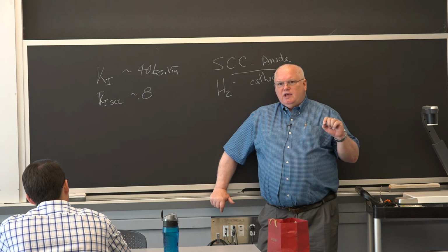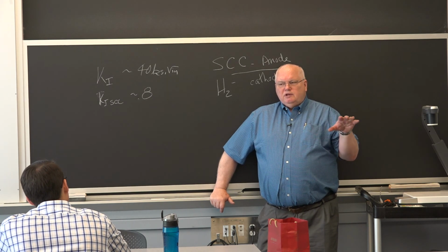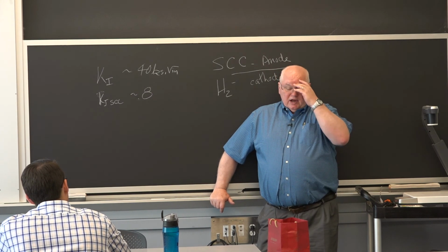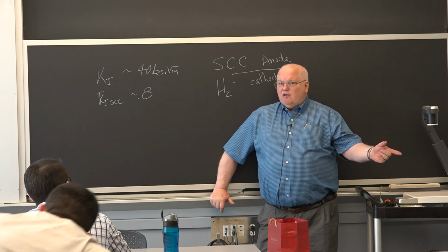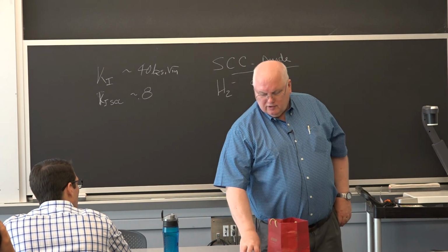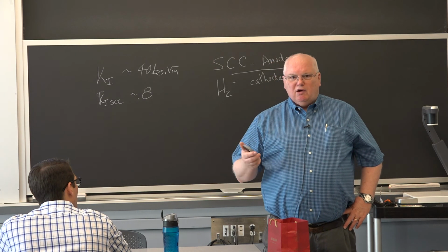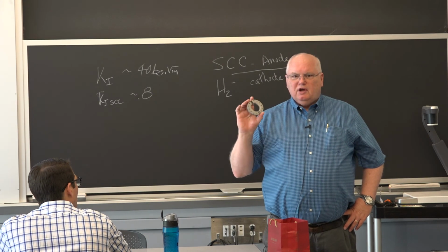And they had fixed it. They had gone from the T6 heat treatment on this washer to a T73. And when they discovered this, they said, oh, we should tell some of the other aircraft groups that there's this problem. So at the time, there were 1,300 Hawks, Seahawks and Black Hawks and stuff around in the world, and so they ordered 1,300 of these washers.